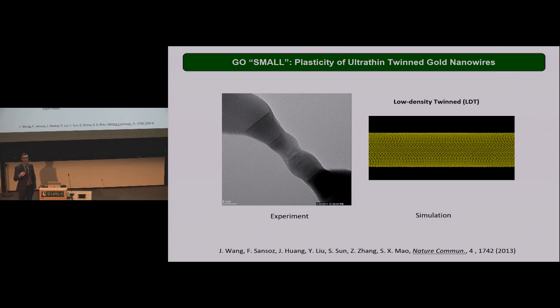And again, it's work with my colleague at the University of Pittsburgh, where we compare high-resolution TEM experiments to the simulation. So let me show you first the case when we have a nanowire, and we will try to understand the strength of these wires. It contains just a few twins that are spaced by more than 6 or 7 nanometers. So let's see the experiment, in situ. What the experiment shows is there is extensive plasticity located between two twin boundaries.